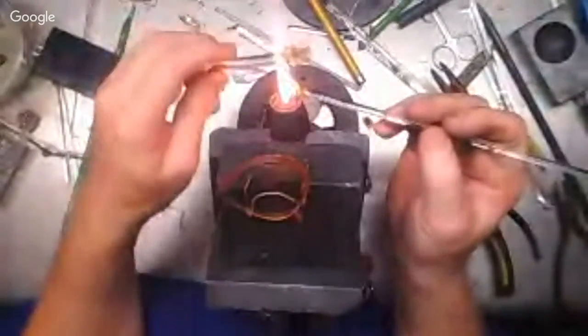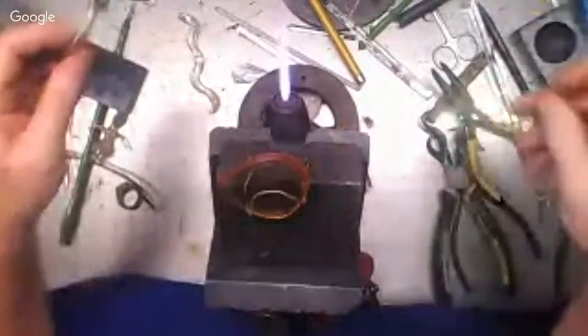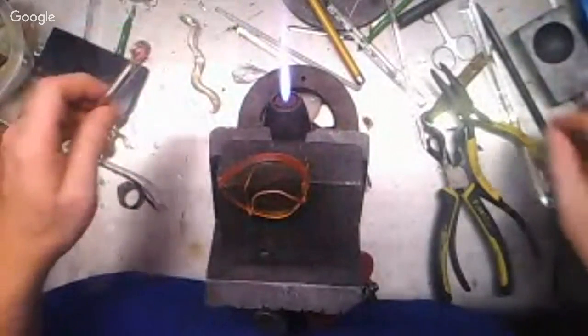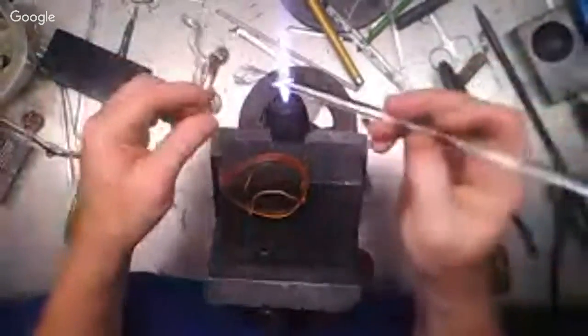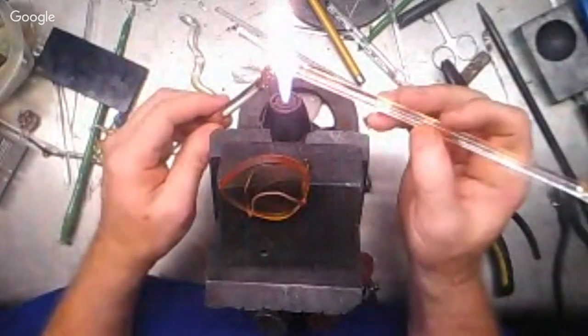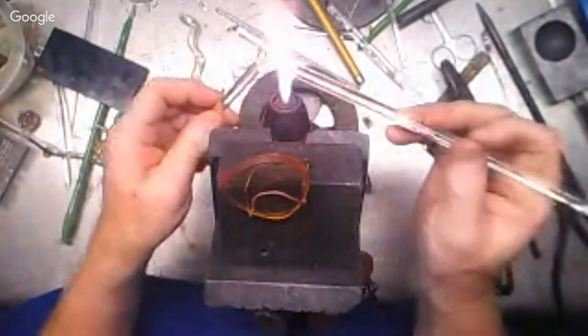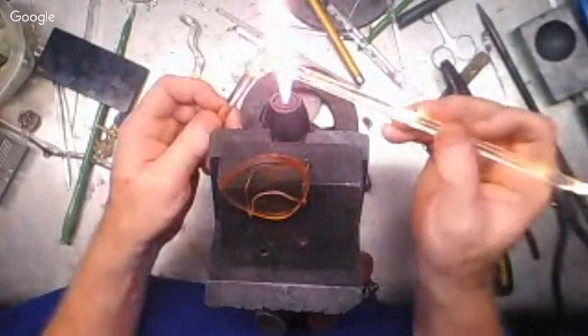Oh, yeah. It tends to heat up faster and sort of retreat into the piece of glass faster than the boro does. And what you've got to do is pinch it from time to time to bring that silver back up to the surface, like squeezing a little boil or something, but it does the trick. Now we're going to get this a little hotter. We're going to encase all of this. And it's not very big at all. And we're going to hope it works. May or may not, who knows. We'll find out in the long run, not the short run.